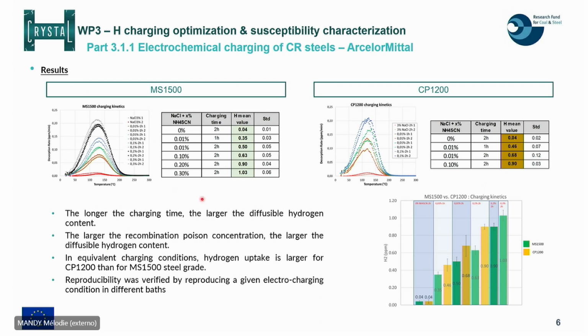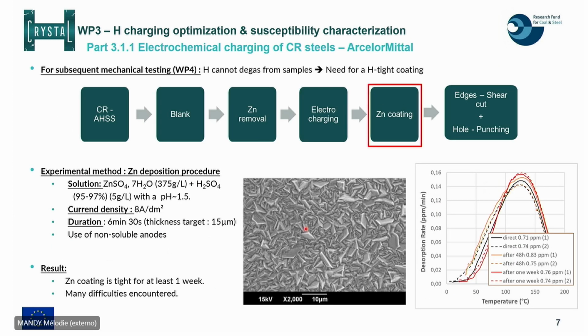Globally, what we can remember is that the longer the charging time, the larger the diffusible hydrogen content. We see also that when we increase the recombination poison concentration, we obtain larger diffusible content, which is logical, as we force hydrogen to enter in the material. When we compare both steels, you have the graph on the right side here, where you can see that in equivalent conditions, the hydrogen uptake will always be a bit larger for the CP1200 than for the MS1500. Finally, ArcelorMittal also verified the reproducibility of those electrochemical charging by reproducing the different treatments in different baths several times. So that was for the part about the electrochemical charging.